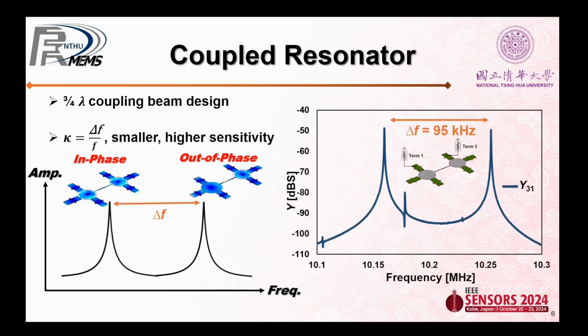The frequency difference of the simulation result is around 95 kHz. The kappa value, defined as the frequency difference divided by the resonant frequency, determines the sensitivity according to the mode localization theorem. The kappa value from simulation is around 9.3 x 10^-3. Typically, the smaller the kappa, the higher the sensitivity. However, if it's too small, it may become difficult to distinguish between the 2 modes.